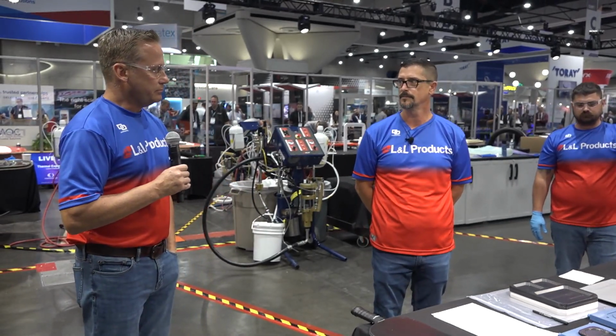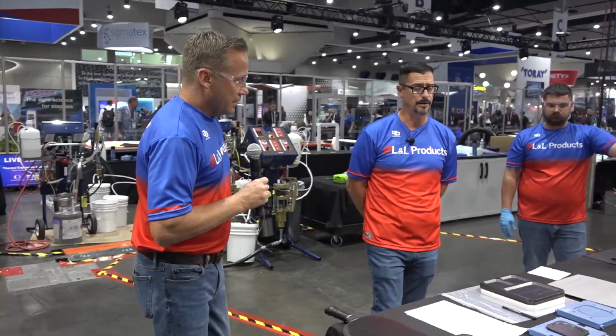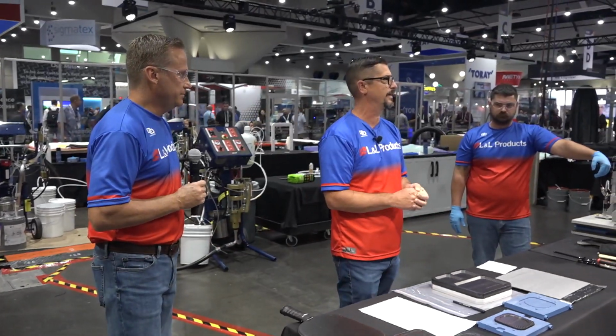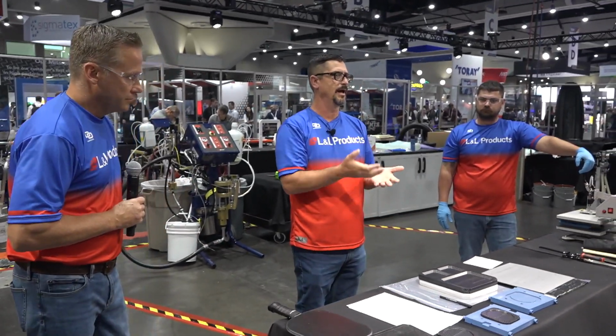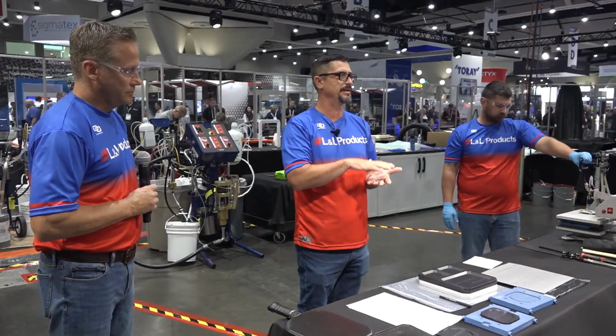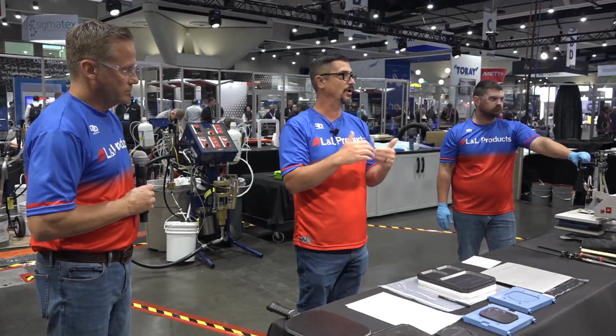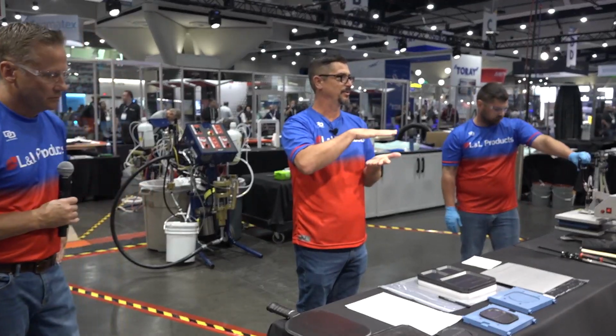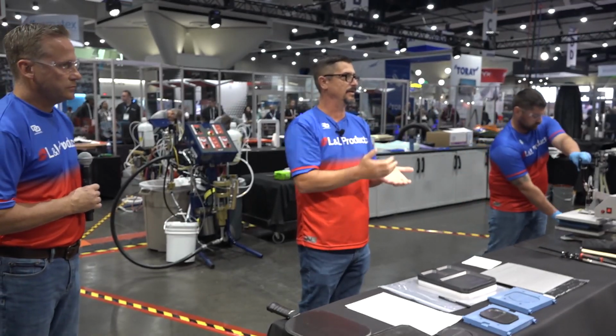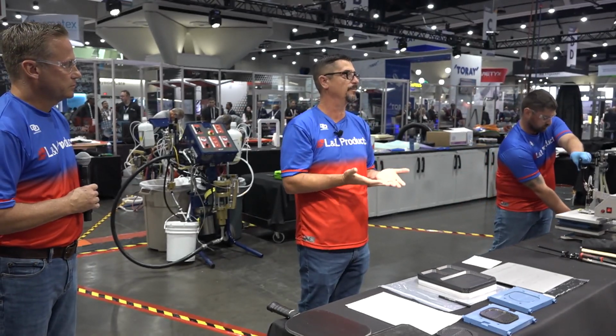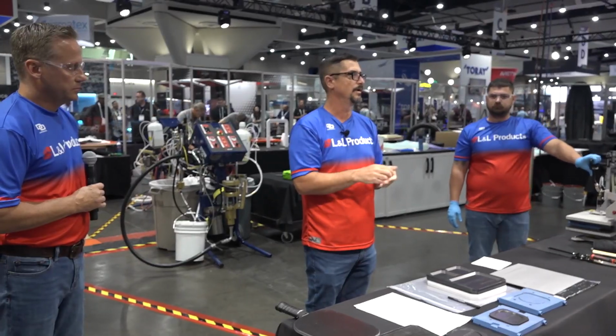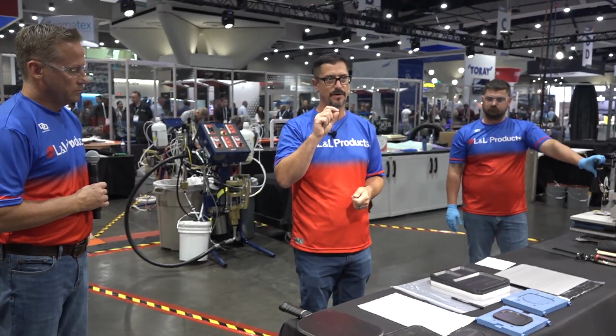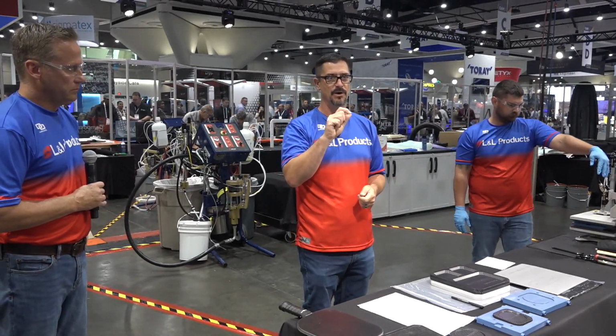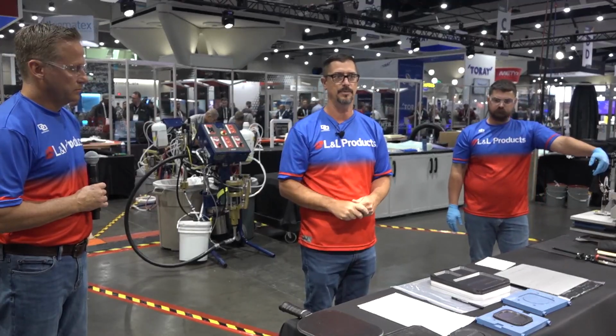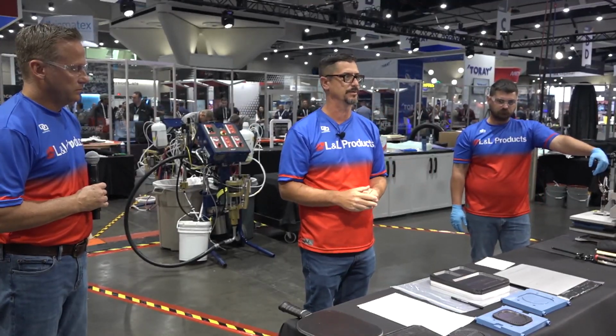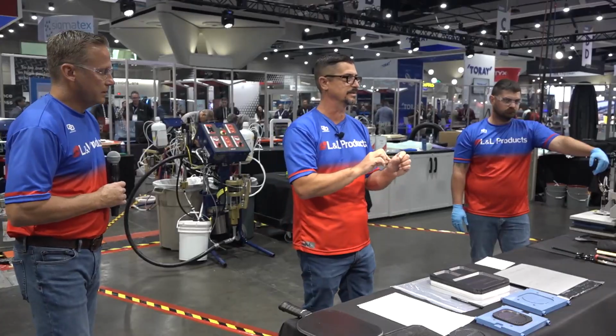And that's especially important when you get into thicker parts, because as the foam is expanding, it's displacing the air in the tool. If there's nowhere for the air to go, you create that die lock, and the foam can't overcome the pressure in the tool itself. So, like Dennis mentioned, it's just a very small vent to create a leak path for that air to escape, and that takes care of any issues with voids in the part or wrinkles at the surface where that air gets trapped.